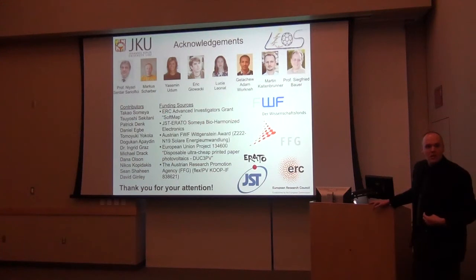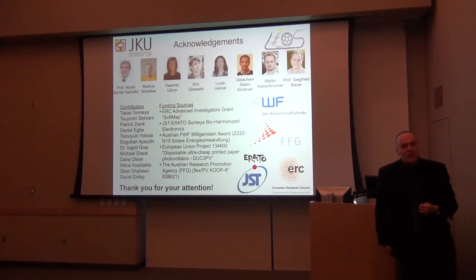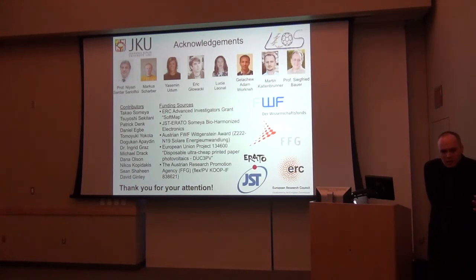So, has anyone looked at, I assume that the emission spectrum of this molecule is well studied, right? It's mediumly studied, not well studied. So you mentioned that you no longer have to deal with excitons here. I assume that what you mean is that the binding energy of the exciton is expected to be really low, right? Yes. We measured it at roughly 5 meV through a pretty crude photocurrent measurement at various temperatures.